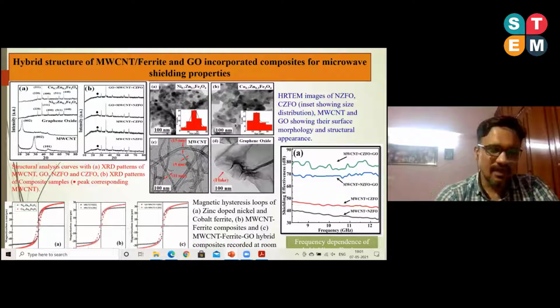After that, we tried to modify the shielding properties, and we selected the components which can enhance the electromagnetic shielding properties. For that purpose, first we modified the magnetism. Like earlier in the previous work, we took zinc ferrite, cobalt ferrite, and nickel ferrite. Here we first modified the magnetization. So we used the site engineering process, in which we doped zinc into cobalt ferrite and zinc into nickel ferrite in appropriate amounts, and we are able to modify the magnetic properties. And after that, we made the composite with the multi-wall carbon nanotube and the graphene oxide. When we studied the EMI shielding properties, we observed an enhanced and modified shielding effectiveness, which is observed for the multi-wall carbon nanotube, cobalt zinc ferrite, and graphene oxide composite.